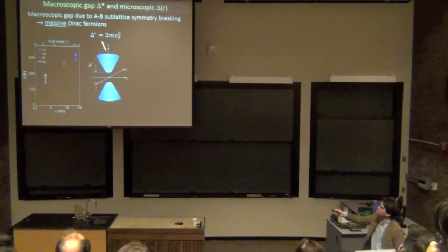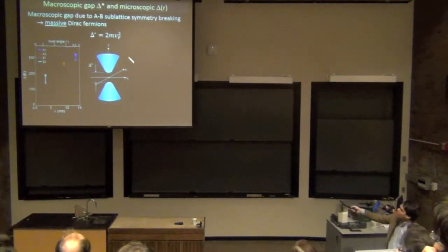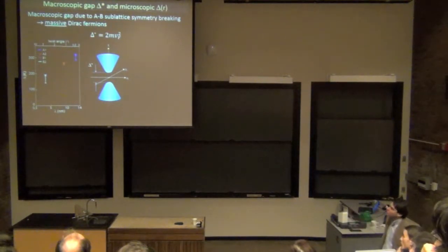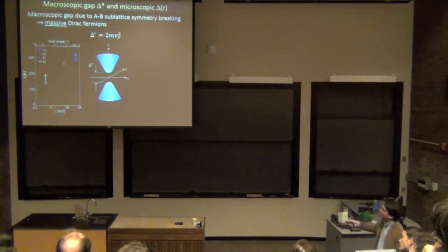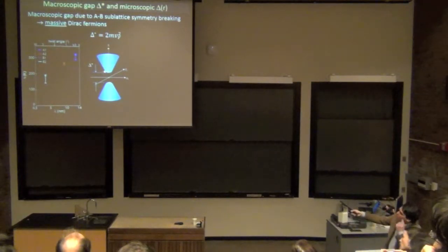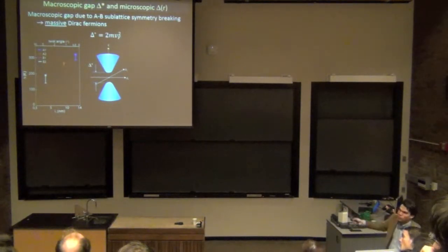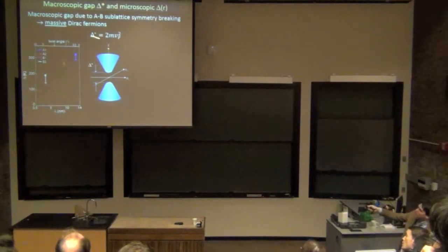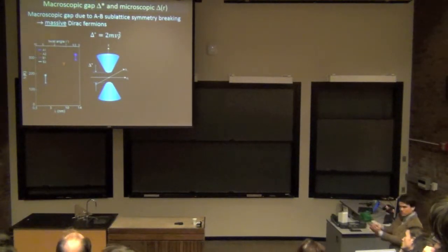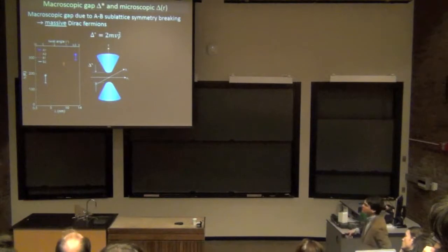Okay, so what do we see? We see what we think is a macroscopic gap due to this AB sublattice symmetry breaking, which points to seeing not massless Dirac fermions, but massive Dirac fermions. So the massiveness comes basically from the curvature of this band here, and you can parameterize the gap with the mass. And moreover, the mass or the gap increases as we twist the angle of the graphene closer to alignment with the boron nitride.